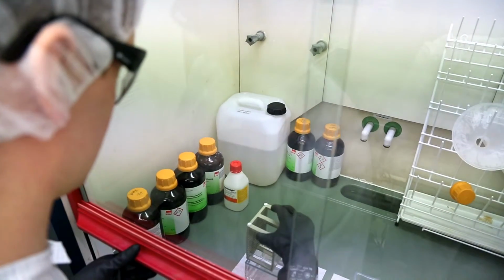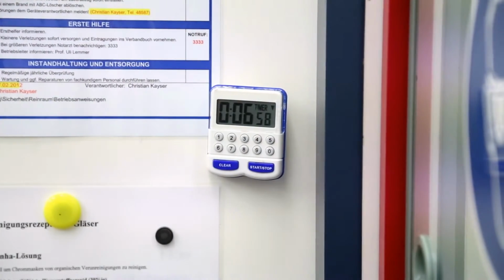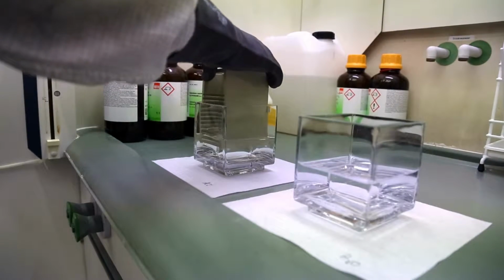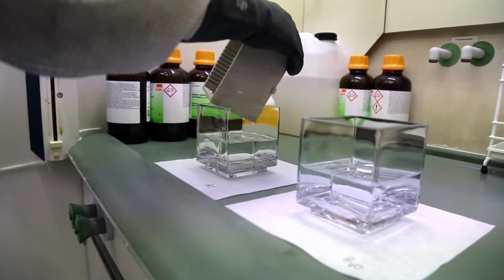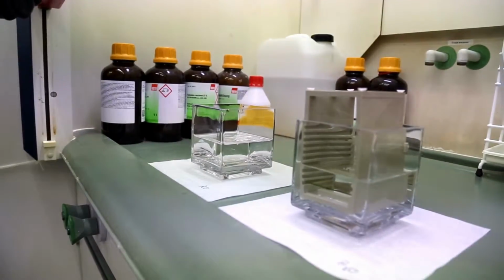In the first stage of the production process, Daniel Baru puts the exposed ITO layer into a container filled with half-concentrated hydrochloric acid. The acid etches away the exposed areas. Subsequently, the ITO layer is washed with distilled water. Since indium is a rare element, its use is one of the reasons for the currently high costs of organic electronics, though not the only one.